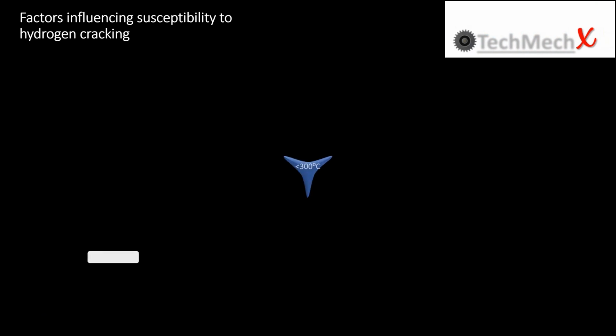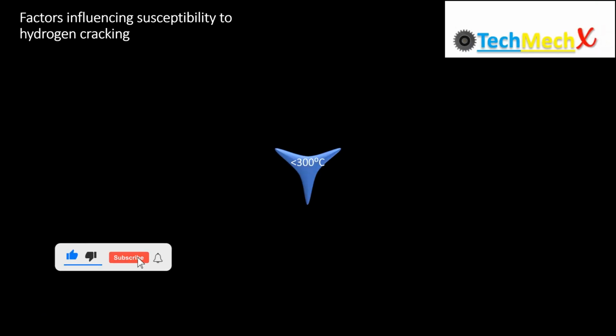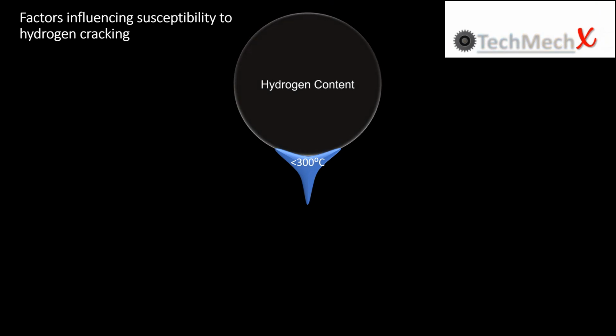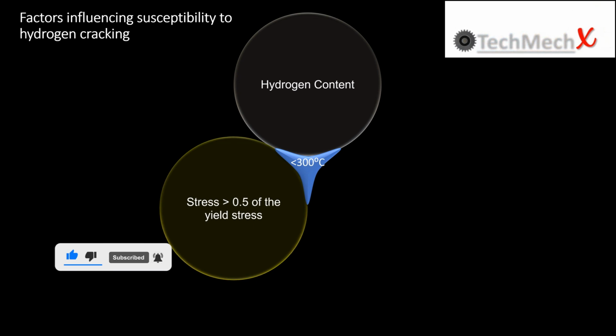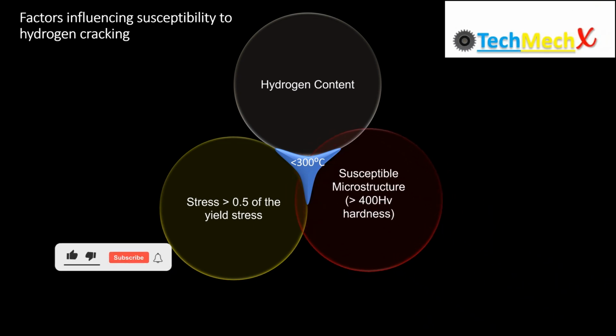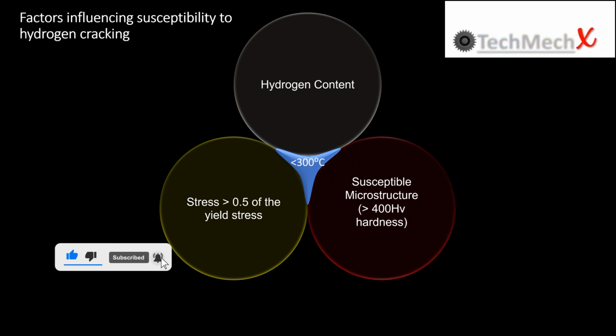Four key factors can contribute to the formation of hydrogen cracks. Temperature: below 300 degrees centigrade limits hydrogen diffusion and increases its embrittling effect. High hydrogen content: a weldment with a hydrogen level exceeding a threshold of 15 milliliters per 100 grams. Stresses greater than 0.5 of the yield stress create a driving force for cracking. Susceptible microstructure: brittle martensite microstructure with high hardness exceeding 400 HV has less resistance to crack initiation and propagation. It is important to note that while heat affected zone cracking is more common, hydrogen cracks can also occur within the weldment under specific conditions.